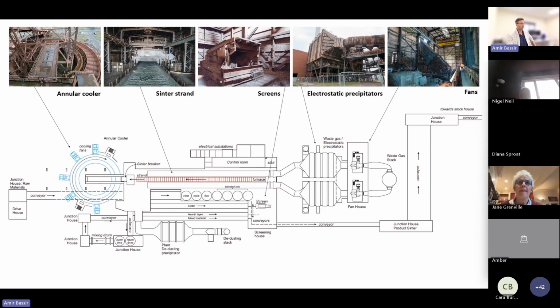The main processes really are raw materials preparation. We've got an automated system of storage bins and hoppers which proportion and mix the materials needed. There's mixing and granulation, where the blend is mixed to create the granules that go onto the sinter strand. The sinter strand is this 185-meter continuously moving strand. At the top end of it, there's a furnace, and the prepared mix is dropped onto there, passes through the furnace, where blast furnace gas is used to ignite the top layer. And once lit, it relies on coke breeze to sustain the combustion.